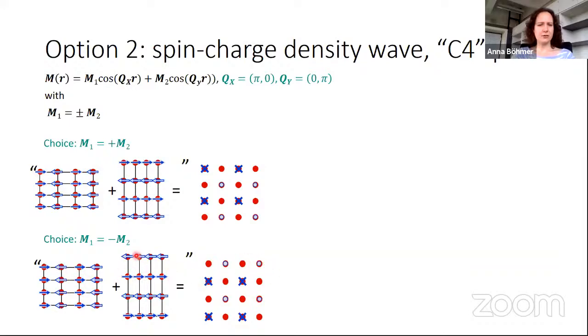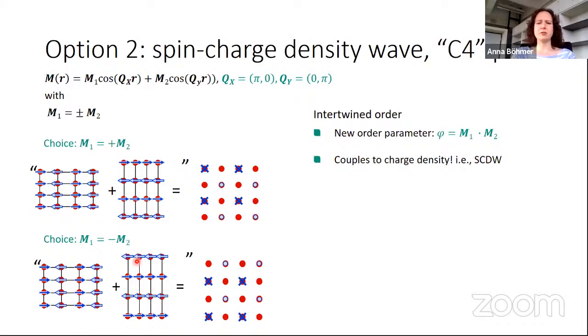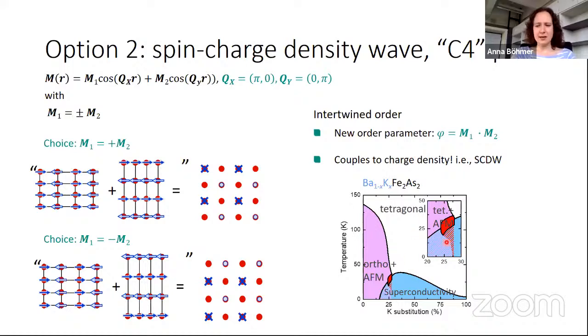You can really add it now. Now these two add, and the first one would cancel, for example. So there's a new intertwined parameter, a new choice. The choice is, are these two parallel, same sign, or anti-parallel, opposite signs? And you can define a new order parameter. And it turns out this is really difficult to measure. What it couples to is local charge density, and we haven't seen that yet. And that is really the phase that was found in the little pocket here. That has been measured using neutron scattering, and it was not only neutron scattering, a couple different magnetic probes. It has been found this is the phase that was found here.